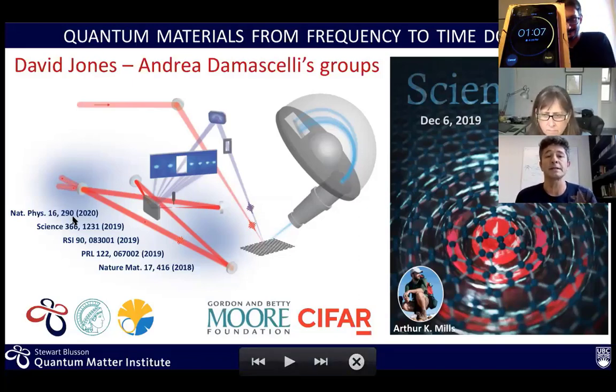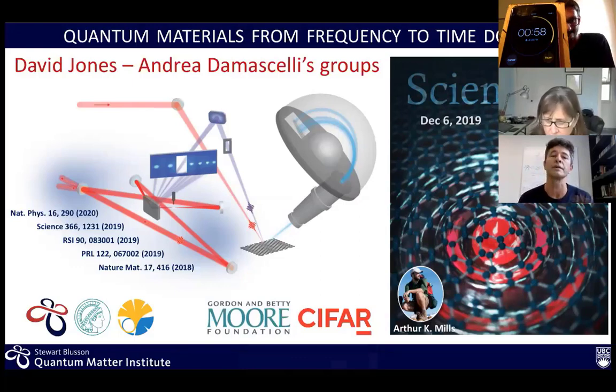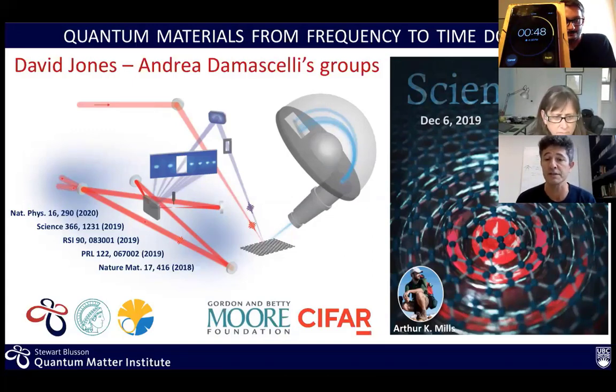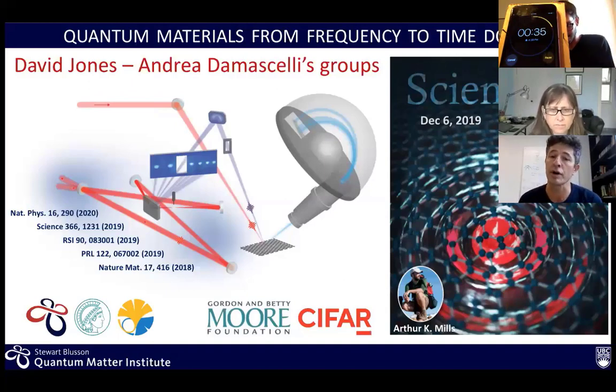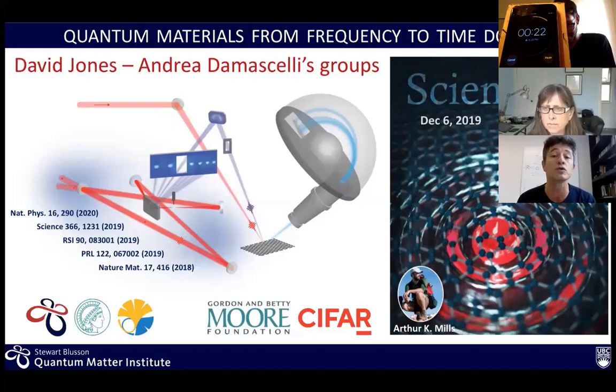This is a system that is unique in the world — very few lasers of this kind — and it allows not only to look at the electronic structure of the solid, but also the dynamics of those electrons. An example is work done by Katie, a student in our group, and Art, a staff scientist. They looked at graphene, the monatomic layer of carbon atoms, and how electrons interact with the vibration of the atoms — called phonons — so-called electron-phonon coupling. For the first time working in the time domain, they could extract a very precise measure of the electron-phonon coupling parameter, which is extremely important because this parameter can give rise, if large enough, to superconductivity.